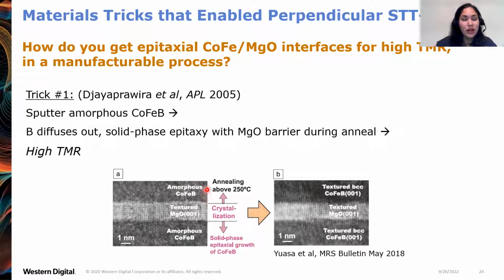Then we put the cobalt iron boron amorphous electrode on top. After the deposition, we do a post-anneal step. And during the post-anneal, the boron atoms diffuse away, allowing the cobalt and iron atoms to arrange themselves on the crystalline template already established by the MgO tunnel barrier. And this process is called solid phase epitaxy. And this is how you get coherent arrangement of atoms across the interface that gives us high TMR values.